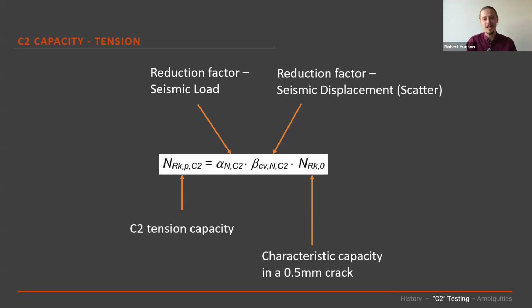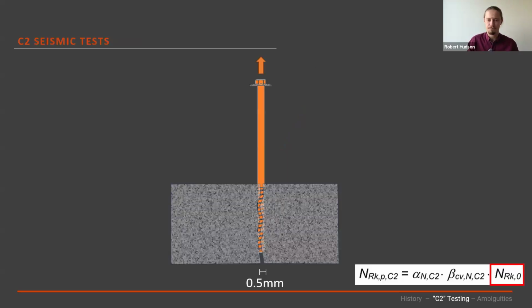And so for the tension capacity, we're going to go through where each of these values come from. So our baseline is just the monotonic tension capacity of an anchor in a crack. It's actually using the 0.5mm crack, which is that moderate seismicity, serviceability baseline performance of an anchor in a crack. And then we have this alpha and beta reduction factor that we apply.